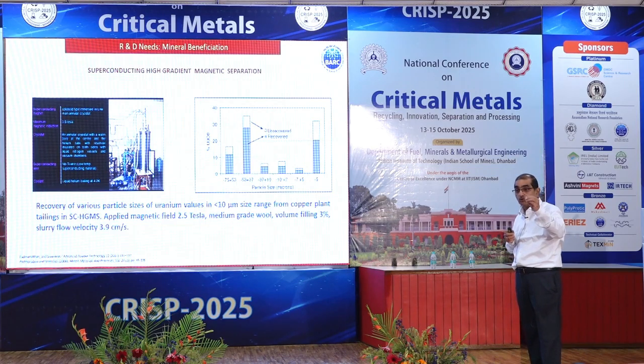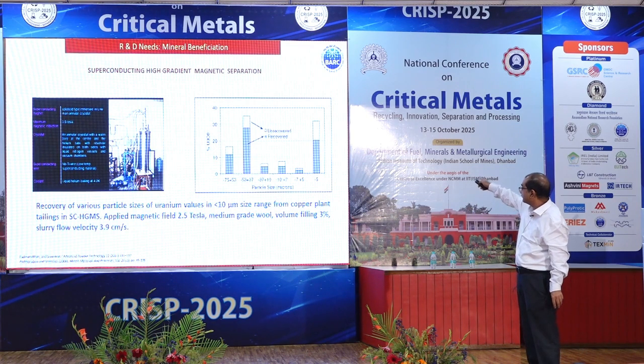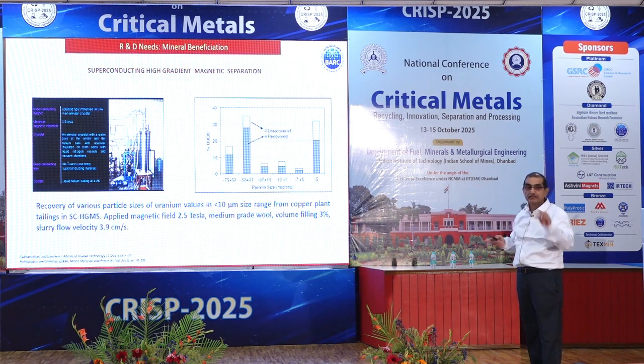So that will go very effectively in picking up particles which are even feebly paramagnetic, up to the size of 5 microns. You can see 15 to 16% of the particles which are feebly paramagnetic in nature can be captured. That is the efficiency of it. We also blame ourselves. That time we did not scale up the superconducting. We need to do that.